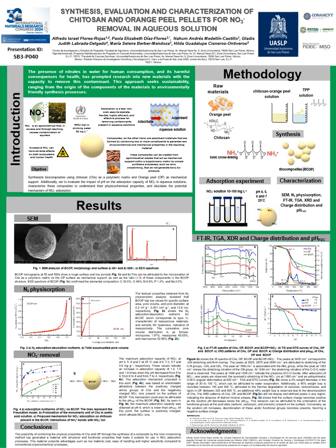After the synthesis was complete, the resulting BCOP were kept in the sodium tripolyphosphate solution for 2 hours at room temperature. Following this, the BCOP was removed from the sodium tripolyphosphate solution and thoroughly washed with distilled water to remove excess. Finally, the BCOP was dried at 40 degrees Celsius in an oven for 48 hours.